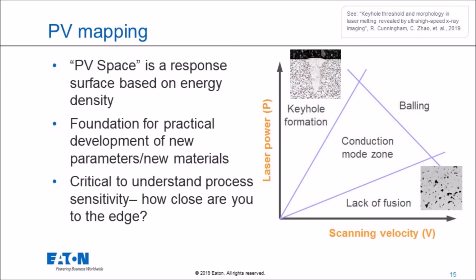If you don't put enough power in and you go too fast, you get lack of fusion, right? You have unmelted particles in your part. And if you go too fast with too much power, I don't have an image here, but basically instead of a single track of melted powder, it kind of balls up, and you get a nonlinear melt pool. So in general, people want to be in the conduction mode zone, which is this triangle here, right?